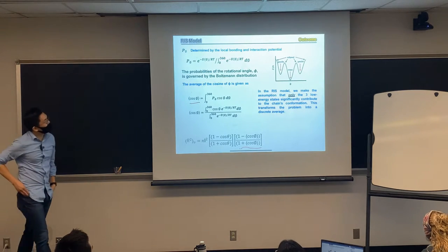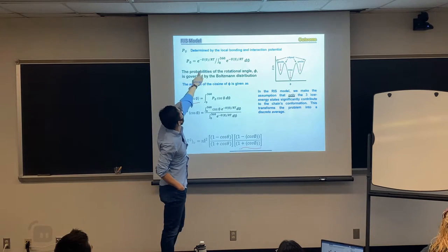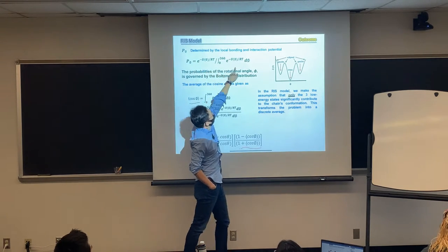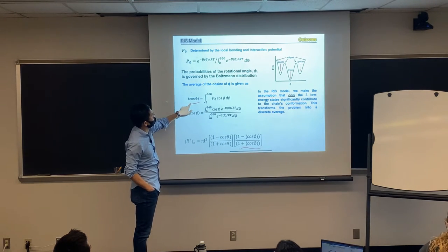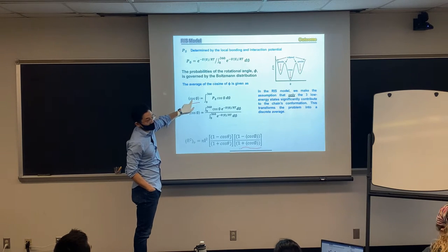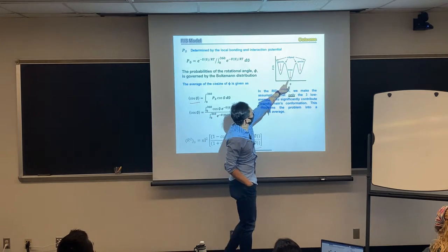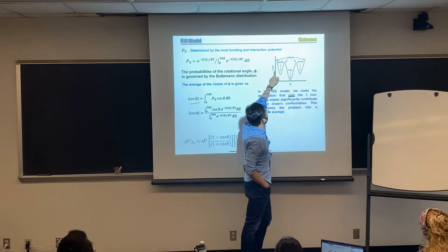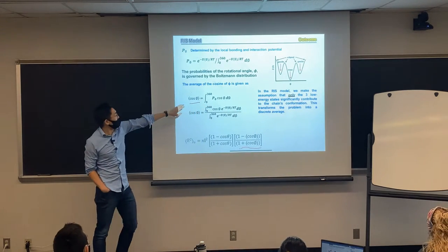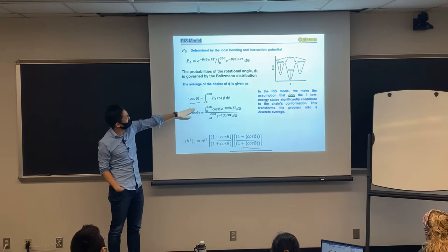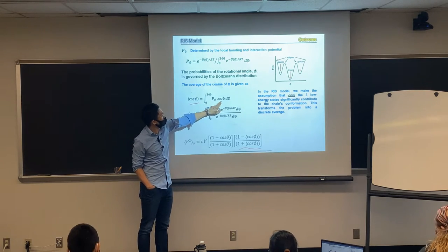So now, as I mentioned, you can use this energy potential map to do an integration. This is basically a normalization factor by integrating everything. This will give you the average cosine theta angle, cosine phi, okay? So that's how this angle is defined. It's not this particular lower point or that point. You need to normalize everything and calculate the average energy potential. That's where the phi angle comes into play. Integrate 0 degrees to 360, probability, cosine phi, d phi.